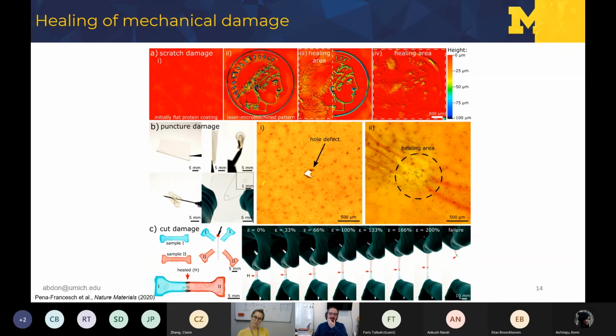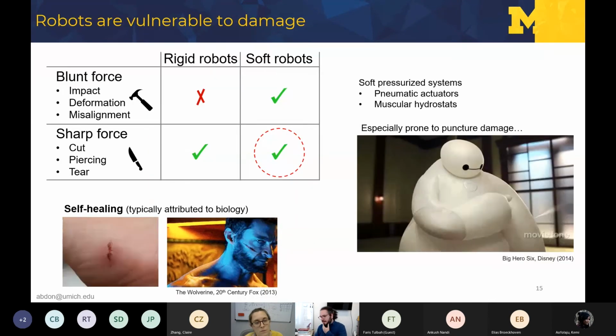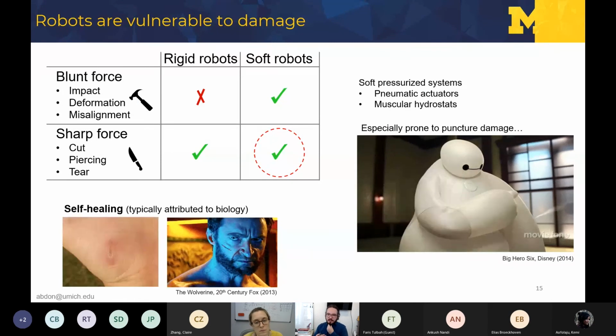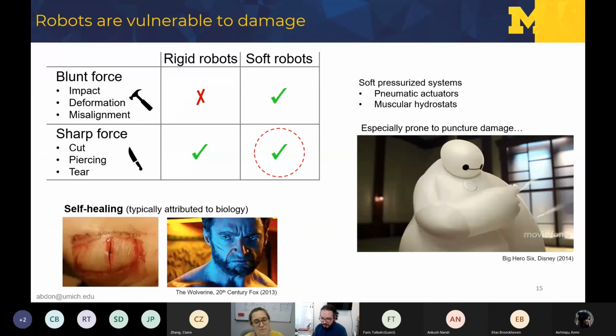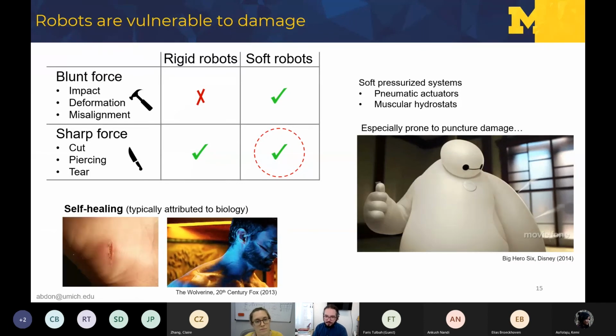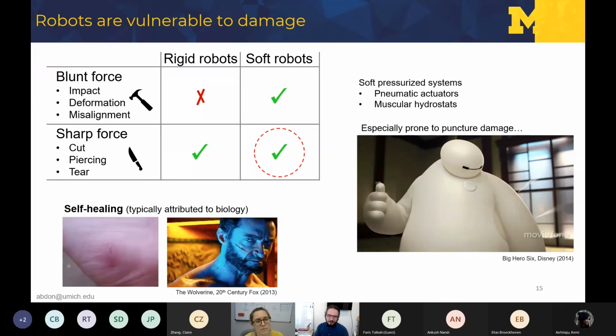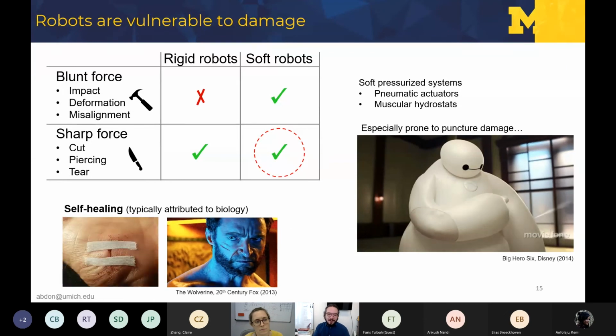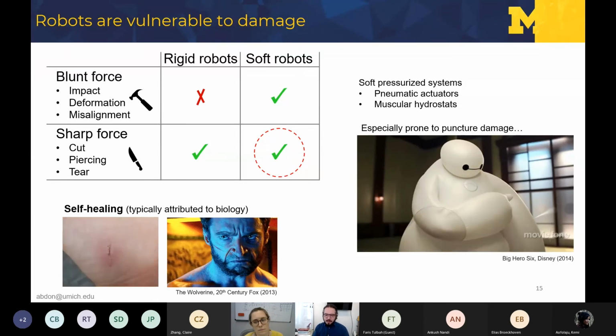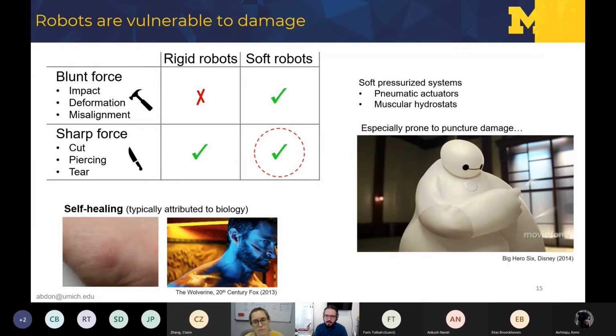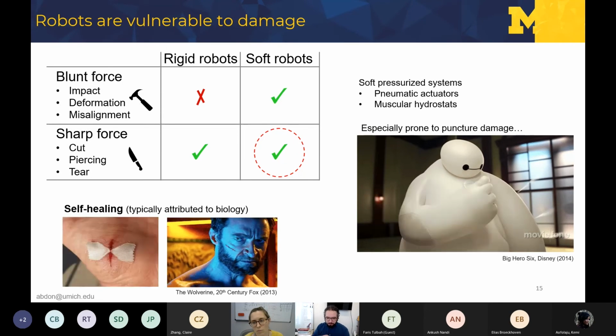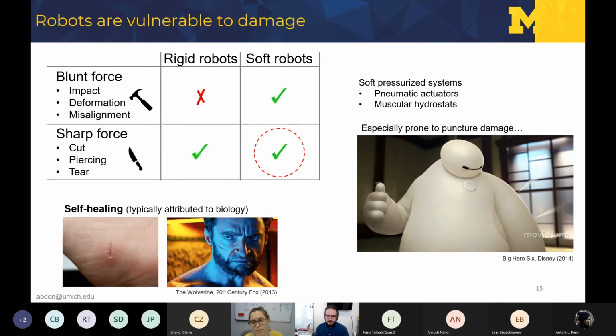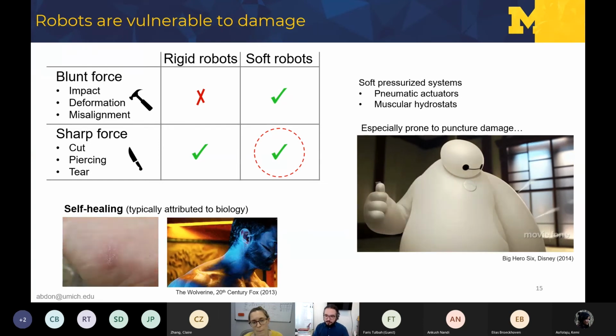But it was great, and we got very excited when we saw that we could heal these small defects, and we wanted to see how we can make an impact in robotics with this, right? Because typically in pressurized systems, which are arguably one of the most common soft actuation methods in robotics, these types of puncture defects are catastrophic, right? And as you can imagine, if you have a pressurized system with a hole, that kills any functionality of your device, right? So this is a big durability problem for these types of actuators. So we wanted to test these self-healing materials in a prototype pneumatic soft actuator.